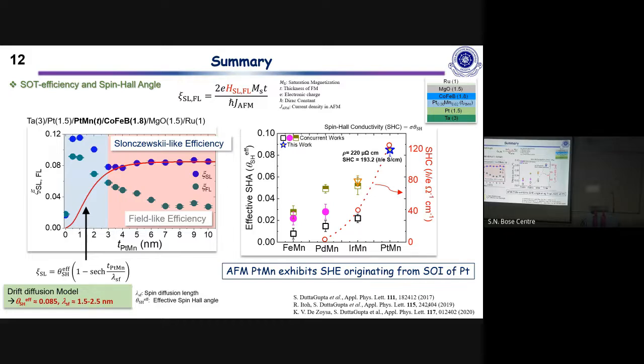How are you sure? Impurity scattering. There could be a contribution from the impurity scattering, which is probably why we have a difference. But the motivation of this work was to find out whether this antiferromagnet is a source of spin Hall angle or shows spin orbit torques. That is why we compared our experimental data with first principle calculations, just considering the bulk spin Hall.